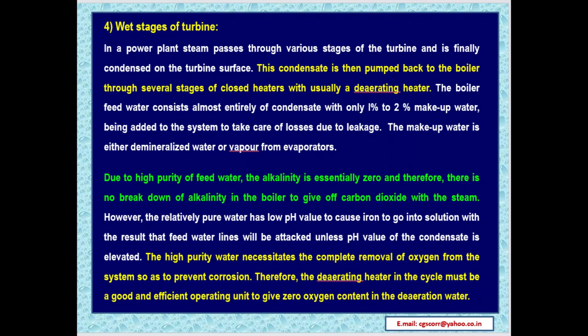The high purity water necessitates the complete removal of oxygen from the system so as to prevent corrosion. Therefore, the deaerating heater in the cycle must be a good and efficiently operating unit to give zero oxygen content in the deaerated water.